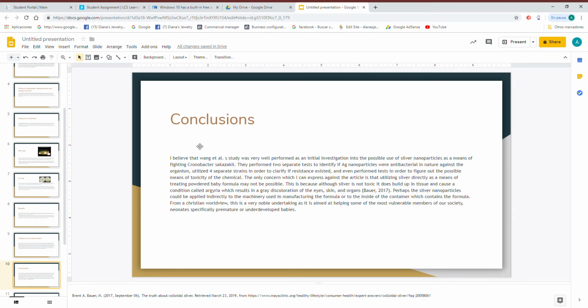My conclusion: I believe that the study by Wang et al. was very well performed, as the initial investigation into the possible uses of silver nanoparticles as a means of fighting Cronobacter sakazakii. They performed 2 separate tests to identify if the silver particles were antibacterial in nature, which is good, because you want to try it out a bunch of different ways and see if you get the same results. They utilized 4 separate strains, which is important with bioorganisms, because oftentimes it's possible for separate strains to have different levels of resistance to certain chemicals.